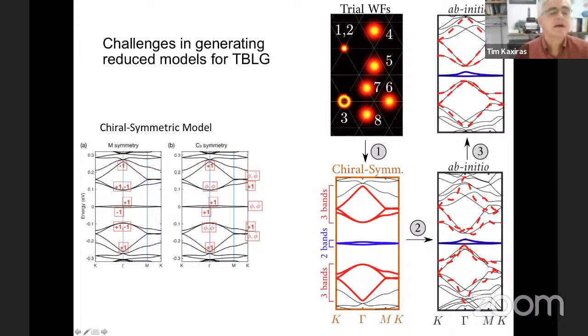And then the next states, labeled 4 and 5, are centered in the AB and BA regions, at the centers of these two large triangles, where the low energy atomic configurations exist. And then we have 3 more states, 6, 7, and 8, which are centered at the domain wall boundaries. And we need all of these 8 states to capture the band structure. So we start with the chiral symmetry states as guesses, and we use the proper combination to reproduce with a few adjustable parameters the full band structure of the system.